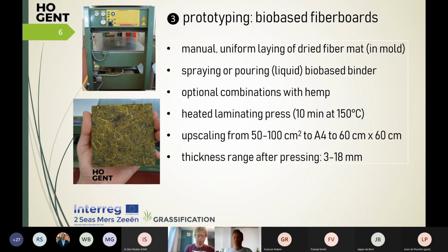So then we proceeded with the actual prototyping experiments. We have developed 4 types of prototypes. The first one being bio-based fiber boards. For this, we manually laid out a dried fiber mat in a mold under the laminating press. We applied bio-based binders, different types of bio-based binders. We tested some combinations also with hemp, and then we subjected the grass to pressing for about 10 minutes at 150 degrees. We started with small scale samples of about 10 by 10 centimeters, and then upscaled this to A4 format. And finally, we managed to produce panels of about 60 centimeters by side.